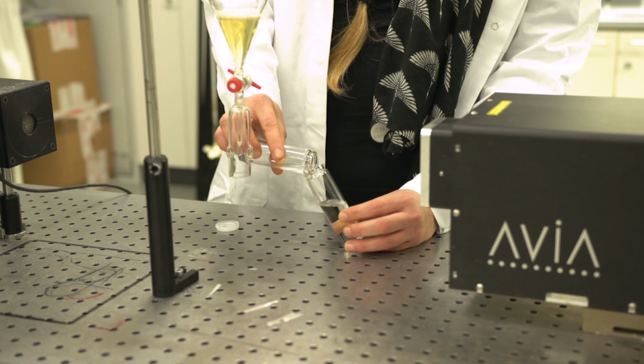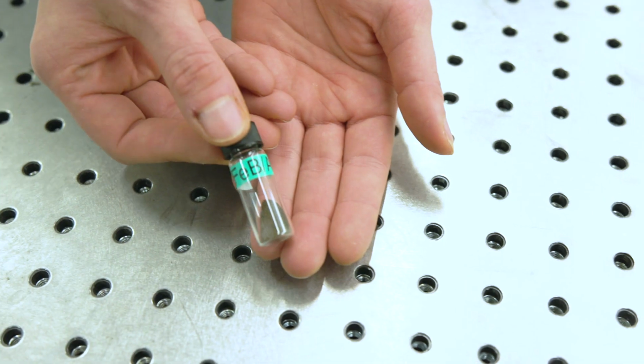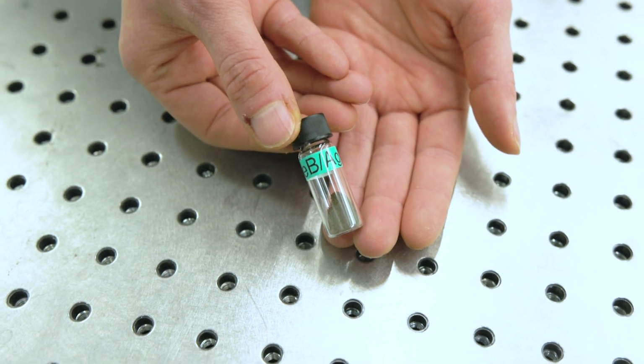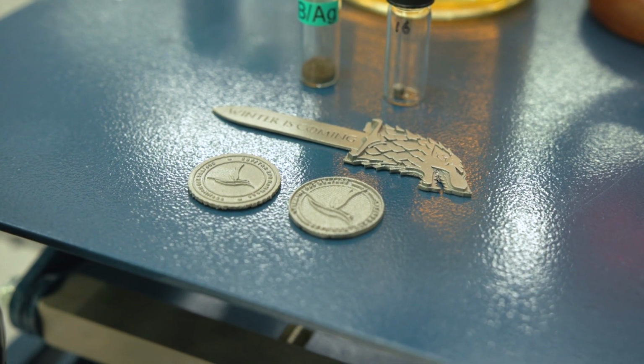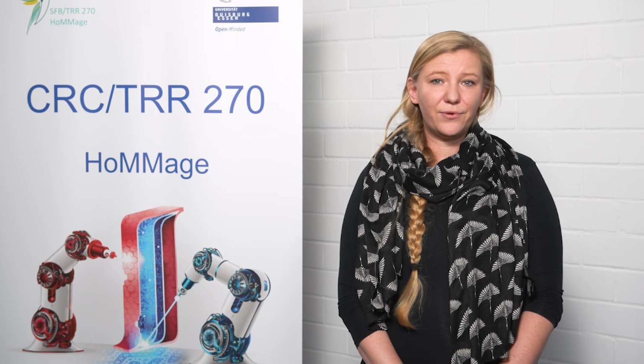By mixing the resulting colloid with the permanent magnetic micropowder and subsequent drying, we obtain our nano-additivated powder that we investigate extensively in suction casting, a process that mimics kind of the powder bed fusion, but also in real powder bed fusion applications. We found that printing of the magnetic powder that contains just 1 weight % nanoparticles leads to as-built parts showing a drastic increase of the permanent magnetic properties, which is already great. We, here in A11, address the complete process chain, starting from the nanoparticle synthesis to the analysis of the final product, including in-depth magnetic, chemical, and microstructural characterization within the TRR 270 infrastructure.